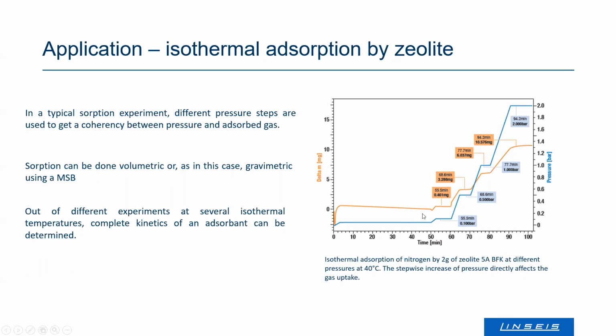With a classical thermal balance, you would have a huge influence when you change the pressure, because the balance unit is also seeing the same pressure, and therefore you have an artificial signal that you have to somehow calibrate. In the magnetic suspension balance, you can directly operate under pressure, and this mass increase you see is not because the pressure is causing the signal to change. No, this mass increase is a real mass increase because the sample mass changes. Why? Because it's adsorbing this inert gas, in that case nitrogen. And out of studies like this, you can do absorption kinetics, you can do diagrams, pressure dependent, temperature dependent, how much gas can be absorbed under certain conditions by different materials, which is something a magnetic suspension balance is typically designed for.